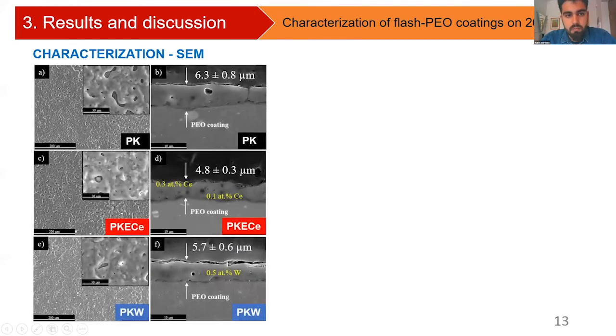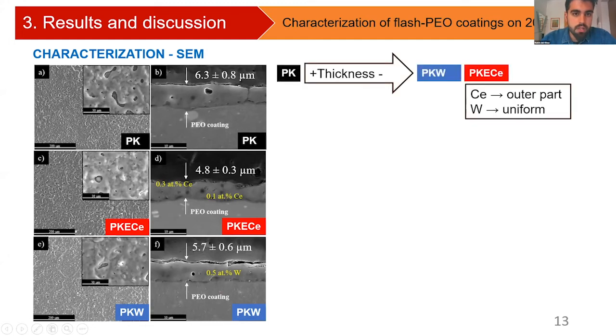Regarding the micrographs obtained by scanning electron microscopy, we obtain a similar porous-like morphology, which is typical for this type of coatings, and we obtain a thickness value for inhibitor-free PEO coatings in comparison to inhibitor-containing PEO coatings. We also confirm the incorporation of cerium and tungstate species in the coating structure. In the case of cerium, it is incorporated in the outer coating part, while in the case of tungstate it was incorporated uniformly in the coating structure.